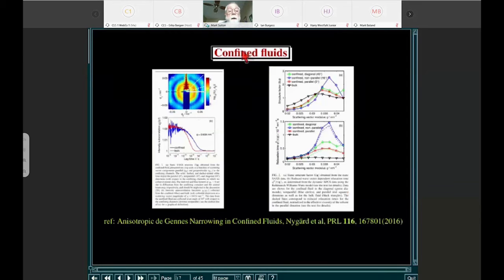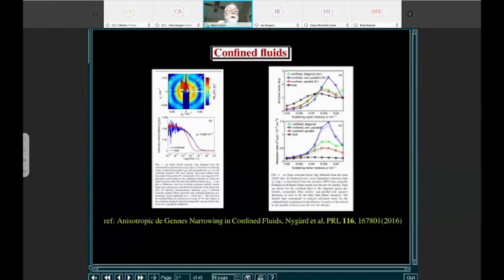So, one example of looking at interesting equilibrium fluctuations is what happens when you put your particles into a confined channel, where the channel size becomes comparable to the particle size. In scattering, we can see the small angle scattering from the particles, and we can look at the difference in the time constants, or the XPCS fluctuations, when we look perpendicular to the channel and parallel to the channel. When we do that, we see the correlation functions have different time constants, and we can plot up the different time constants. And so this is an example of how the de Gennes narrowing depends on the direction the particles are flowing in a channel.